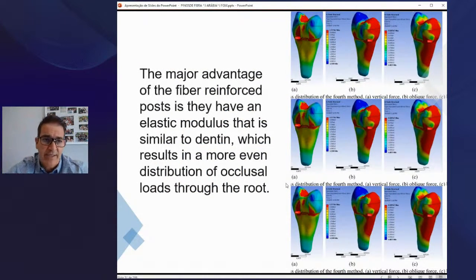But the major advantage of those fiber reinforced posts, and this is a main consensus, is that they have an elastic modulus that is similar to dentin, which results in a more even distribution of occlusal loads through the root. There are a lot of studies showing this. You have something to help absorb all the occlusal loads, so it preserves the tooth structure and avoids fracturing. It's a very nice protection for the tooth.